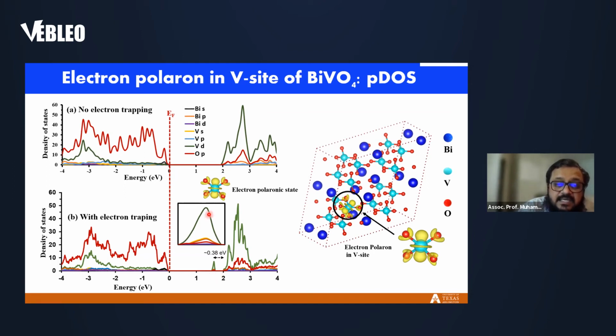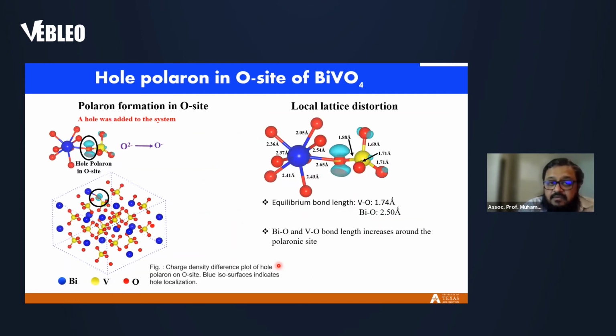This green line has the same color scheme we used for the pristine and the doped one. The green DOS is the vanadium 3d orbital, and it shows the charge density feature of a d orbital. Then we do the hole polaron on the oxygen site. Again, the hole polaron is localized at the oxygen site. It shows a feature of a p orbital, oxygen p. It is formed at one site and also shows the corresponding lattice distortion.